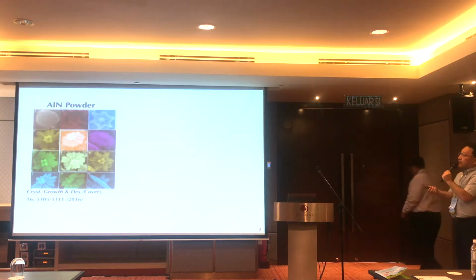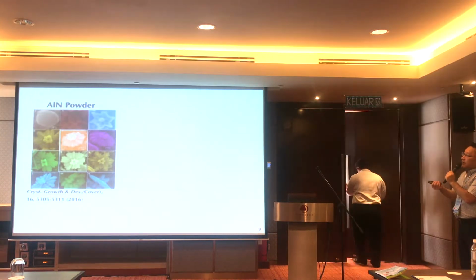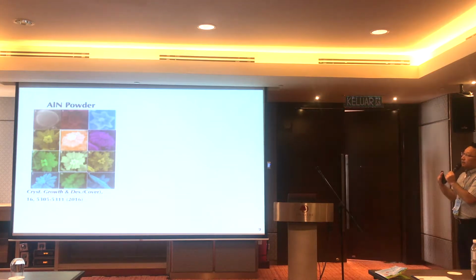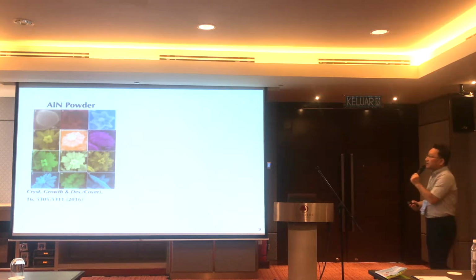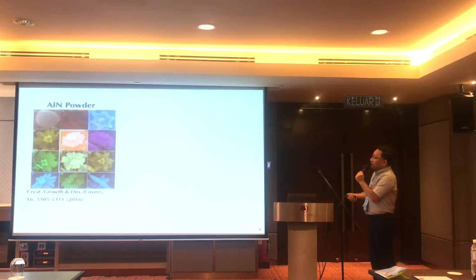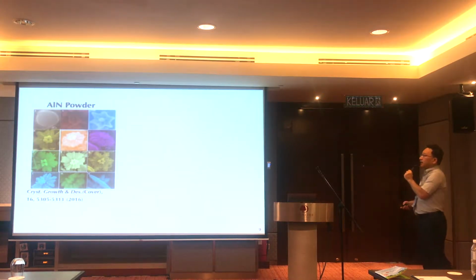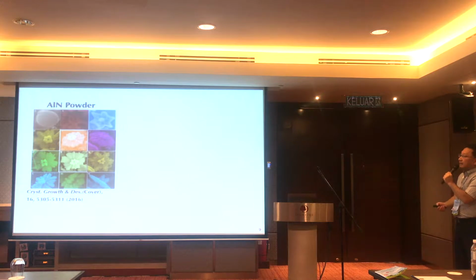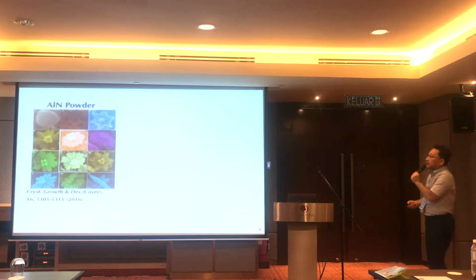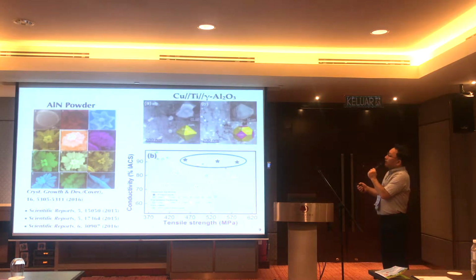We predicted aluminum nitride powder. This is a very important material in the display materials. This was actually chosen as the cover of the journals. We predicted the aluminum nitride topology by using first principle calculations, and actually they synthesized it exactly as the computational predictions. We also designed multi-component systems.